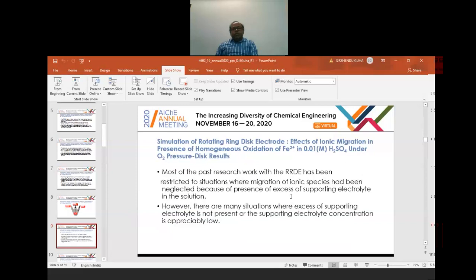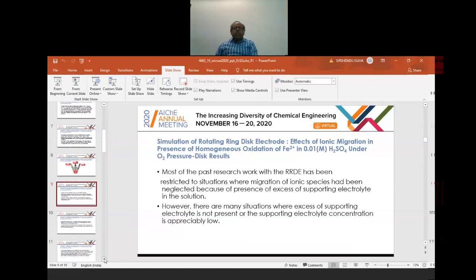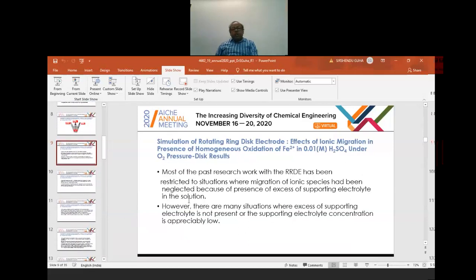Now, most of the past research work on RRDE has been restricted to situations where migration of ionic species had been neglected because of presence of excess of supporting electrolyte. What is supporting electrolyte? Supporting electrolytes are those electrolytes like sulfuric acid, hydrochloric acid, which when used in excess in electrochemical reaction lead to enhancement of the conductivity of the solution and the potential gradient becomes nil. So the migration mode of transport for these situations becomes insignificant.